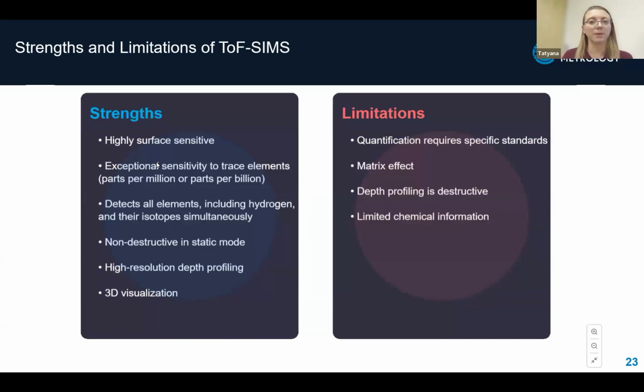And that brings us to the summary of this talk. As we have seen, ToF-SIMS is a powerful analytical technique with some distinct advantages, but also a few limitations. On the strength side, it is an exceptionally surface-sensitive method with incredible trace element sensitivity, down to parts per billion. Unlike many other techniques, it can simultaneously detect all elements, even hydrogen. In static mode, we can analyze samples non-destructively, while depth profiling allows us to create high-resolution 3D visualization when needed.